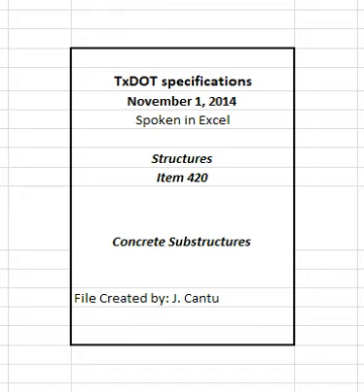4.7.3 Workability of concrete. Place concrete with a slump as specified in Section 421.4.2.5, Slump. Water may be added to the concrete before discharging any concrete from the truck to adjust for low slump provided that the maximum mix design water-cement ratio is not exceeded. Mix concrete in accordance with Section 421.4.6, Mixing and Delivering Concrete, after introduction of any additional water or chemical admixtures. Do not add water or chemical admixtures after any concrete has been discharged.